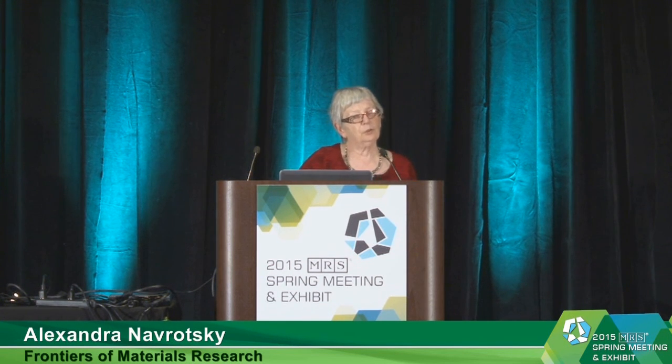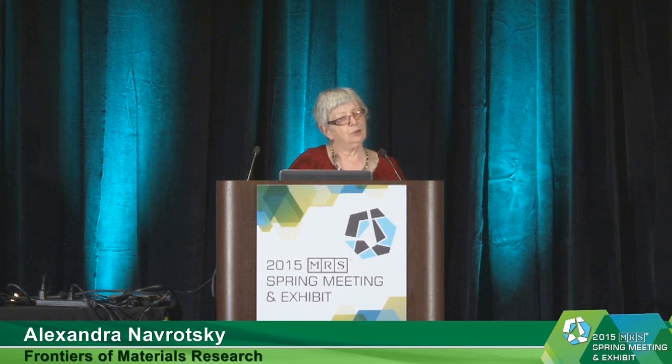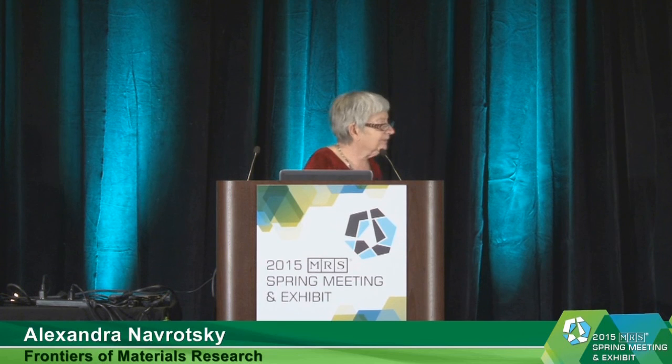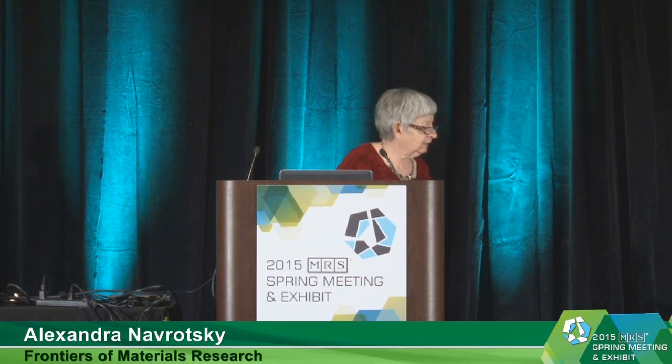Remember, the definition of the term surface energy, rigorously, is the change in the energy of the material with the change in surface area, nothing else changing. If in fact you're in a multi-component system, everything else changes, and you have relaxed those constraints, and you may in fact then have a stabilization of the whole system by keeping stuff in the grain boundaries, and keeping the grain boundaries there because there isn't a better place for the other stuff to go. So think of it as a standard state. Think of the grain boundary perhaps as a place where it could create a standard state. Yeah, exactly.